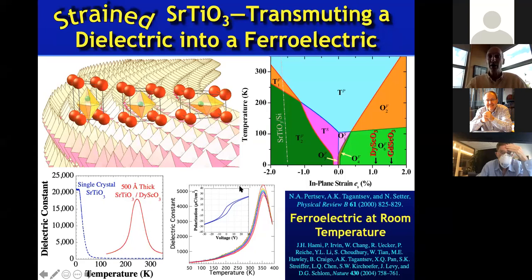And if we strain it even more by putting the strontium titanate on top of dysprosium scandate, you can see that this peak, which is telling you where the material becomes ferroelectric, where it goes from being paraelectric to ferroelectric, that transition temperature goes above room temperature. And it's possible now, even at room temperature, to see this ferroelectric ground state stabilized using this strain engineering trick.